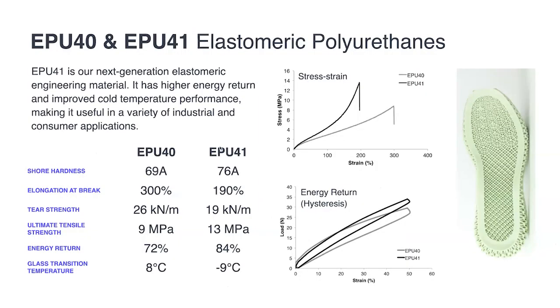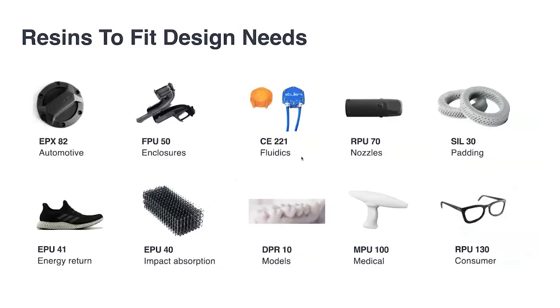You can make elastomers by extending the length of the polyol, and you can make elastomers with a TG close to room temperature or well below room temperature. So you can make elastomers that are dissipative of impacts or energy returning, depending on where you put the TG. And so what turns out is that we can now make a wide range of polymeric properties, but the details are you have to tune the resin to the printing process because of the physics of viscosity, light intensity, thermal window control. And so every resin has to be tuned to the process.